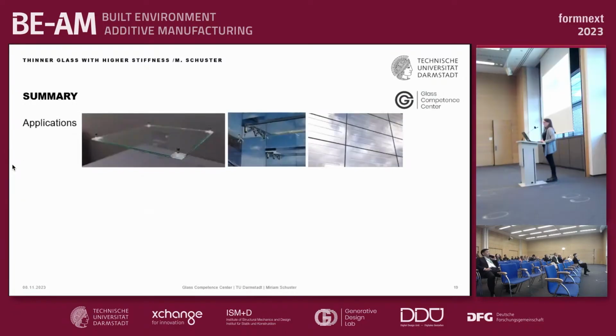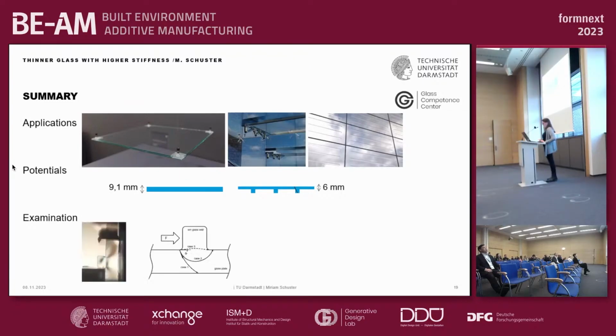So I want to summarize. We see different applications of AM glass in the built environment, starting from point fixings or linear bearings, but I think the biggest potential lies in the stiffening of thin glass. I showed the example where we could reduce the glass thickness from 9 millimeter to 6 millimeter by only applying 3 reinforcements. And we did some shear tests where none of the samples has broken at the interface of the base plate and the AM wall.